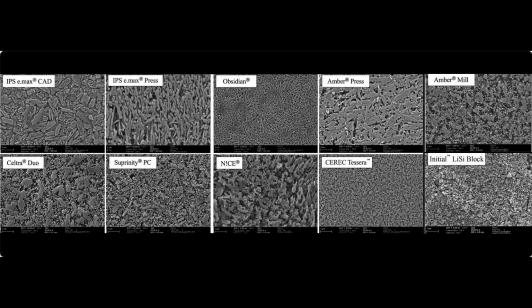So you can see them here, all the different brands. You can see all these little needles that the material has that allows them to be the material of choice for most clinicians, right? Lithium silicates. But it's also a glass ceramic, so you can stain it just like we stain the glass ceramics. You can, but it's really hard to polish. So glass lithium disilicate is really hard to polish. And now we can only mostly finish it in the oven, right?